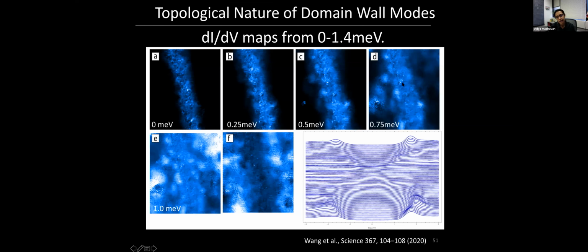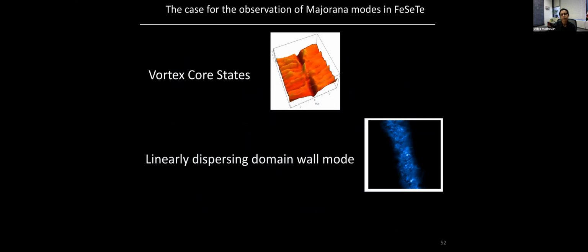So this is exactly what you would expect for a topological state, because for a topological state, what you expect is that you should see states at all energies inside the gap, but the spatial extent of the state should increase as you get further and further away from 0.